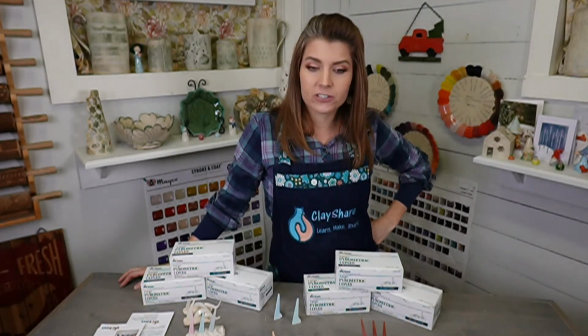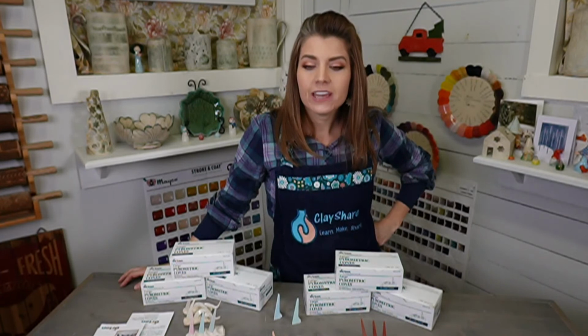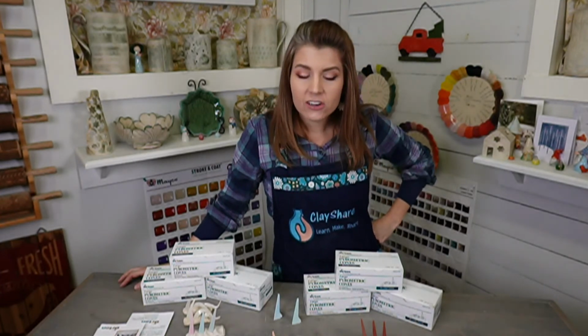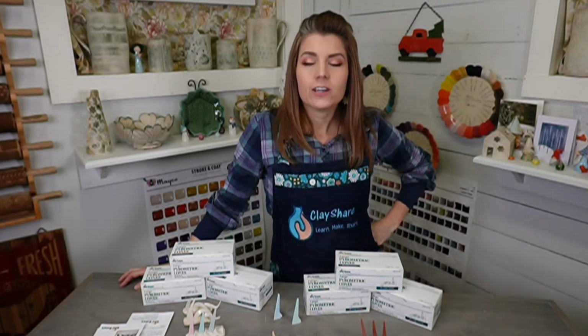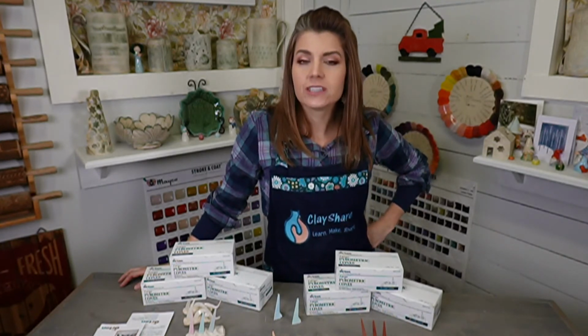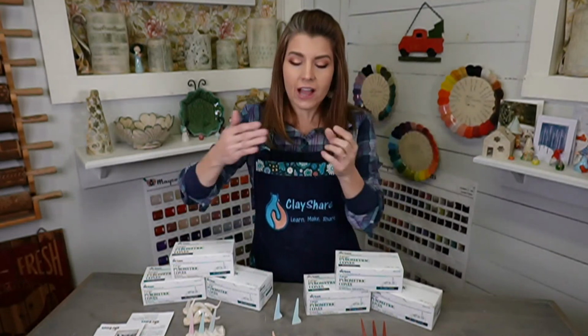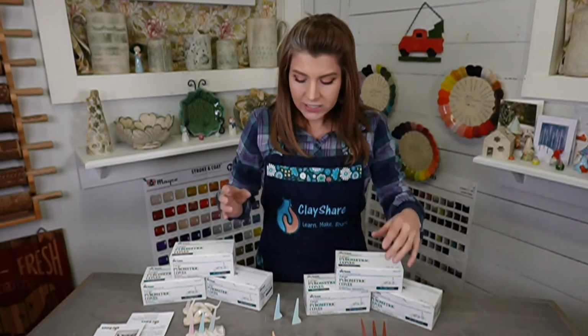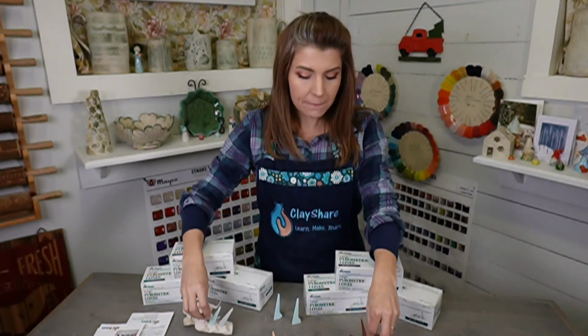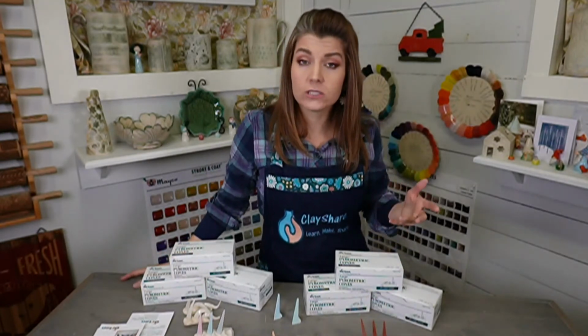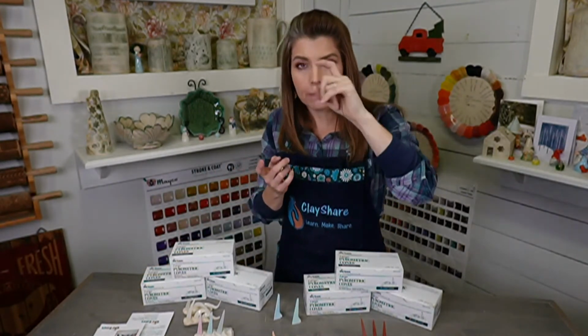So what about tweaking temperatures with a kiln sitter with the mini cone, if moving it slightly to a thicker or thinner center? So Martha, when you're firing with a kiln sitter and you're using the little mini cones, what I try to do is I do put the sensor bar in the center still. You do want to do that. You don't want to try to move it off to one side or the other. Just leave it in the middle. And what you'll do is you'll still want to have a cone pack in there so you know what's happening. And if you find that you're needing a hold on those pieces, what I do is when my kiln sitter kiln's about to trigger, I'm in the studio looking at it, and you'll see it start to move.